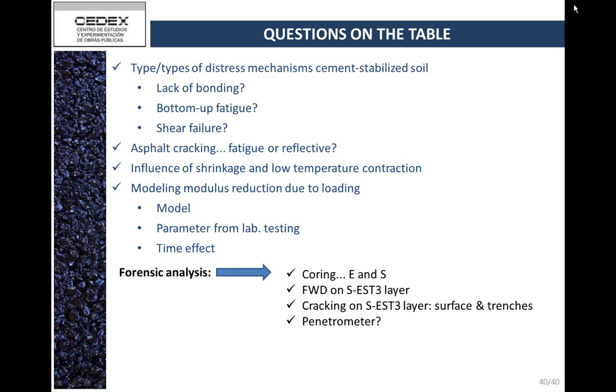But something interesting is that as soon as you lose bond, there's a change in the whole stress distribution in the layer of the cement-treated material, and you'll see that the shear comes up. Because of the debonding, you see exactly the loss in what you described earlier as structural competency. You can actually measure that stiffness loss with a PSPA, for example, and you can see all of that happening. So without belaboring the point, I would urge you to look at that and get back to us if you have further questions. But I think we've got beautiful correlation between what we're hearing from the three parties here. And I agree with what you're saying, Fred.